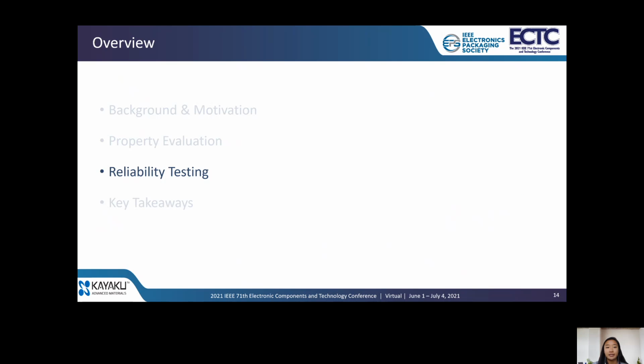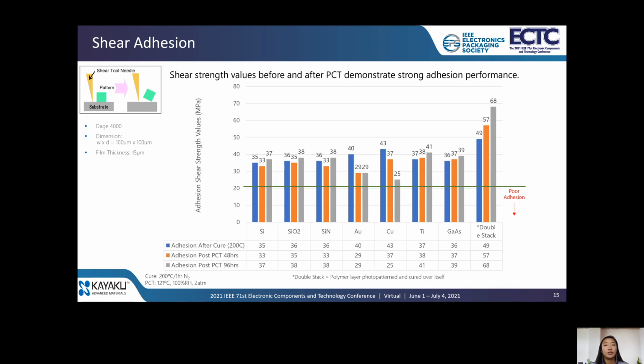So let's get into reliability testing. Going back to the shear adhesion performance, we tested after running test wafers through pressure cooker testing, and we checked adhesion after 48 hours and then again after 96 hours of PCT. This was run at 121 degrees C at 100% relative humidity at 2 atmospheric pressure. And here are the results that we've plotted. To compare the baseline in blue with the PCT results in orange for 48 hours and gray for 96 hours, overall the adhesion of the material did not go below the threshold of what we consider poor adhesion.